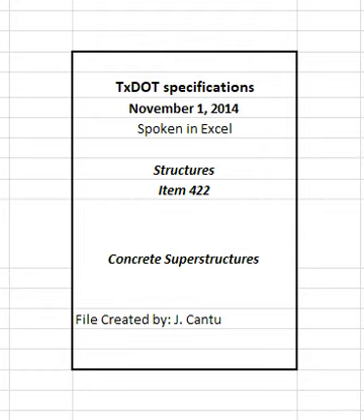Apply final curing as soon as possible after interim curing without damaging the surface finish. Check the adequacy of the curing each day of the curing period. Take corrective action or modify the curing methods as needed to maintain a moist concrete surface. A curing day is a calendar day when the temperature, taken in the shade away from artificial heat, is above 50 degrees Fahrenheit for at least 19 hours, or, on colder days, if the temperature of all surfaces of the concrete is maintained above 40 degrees Fahrenheit for the entire 24 hours.